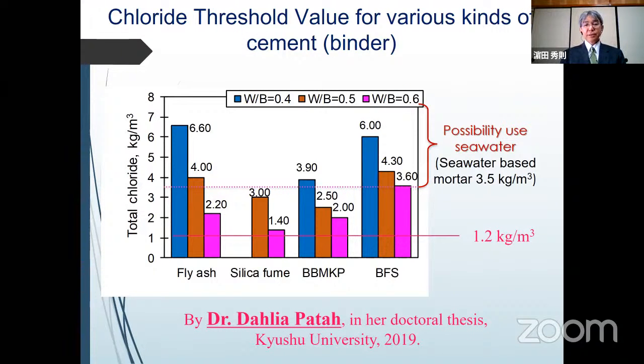However, there is a very interesting and important research result by Dr. Dahlia Patah, Kyushu University, 2019. This diagram shows the chloride threshold for corrosion initiation in concrete mixed with several different kinds of mineral admixtures. If fly ash is used, then the maximum threshold level is 6.60, with a water to binder ratio of 0.4. And if we use blast furnace slag, the maximum chloride threshold level is 6.0, for a water to binder ratio of 0.4. This is much over the chloride content of seawater-mixed concrete, around 3.5 kilograms per cubic meter.